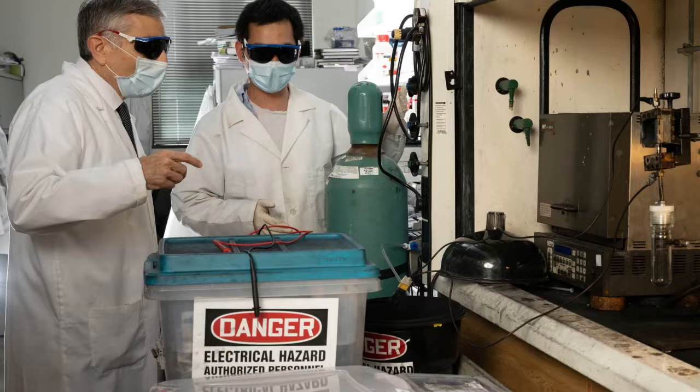Levels of arsenic, mercury and chromium were all further reduced by increasing the number of flashes. Since each flash takes less than a second, this is easy to do, Tour said. According to the researchers, the scalable Rice process consumes about 939 kilowatt hours per ton of material processed, 80 times less energy than commercial smelting furnaces and 500 times less than laboratory tube furnaces. It also eliminates the lengthy purification required by smelting and leaching processes.